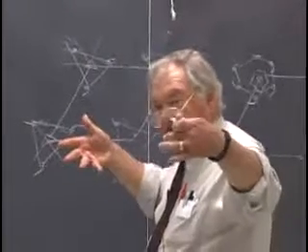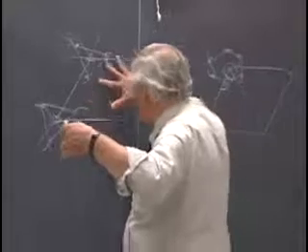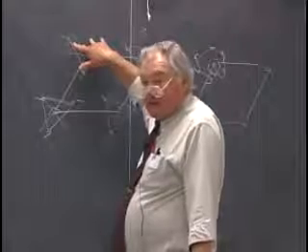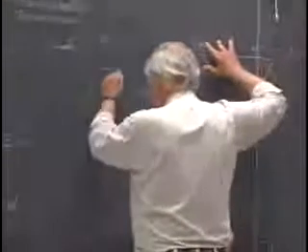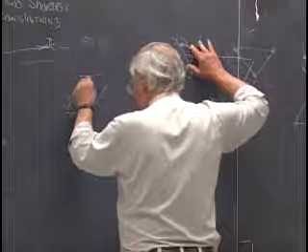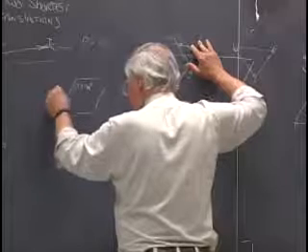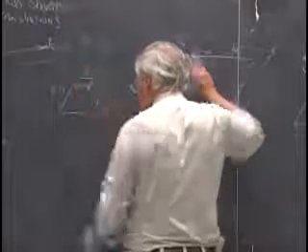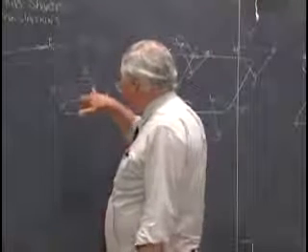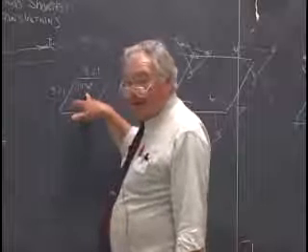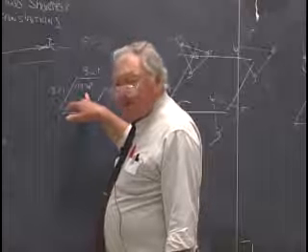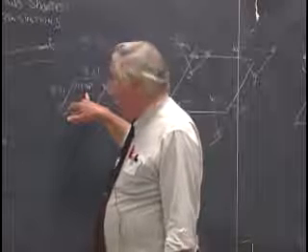specialization of the lattice. Conversely, a lattice can have this specialization only if you place in it a symmetry which demands precisely that specialization. So if you measure a lattice, and this turns out to be 119.99 degrees, and these turn out to be 3.21 angstroms and 3.21 angstroms, that is not a hexagonal lattice, because there's no symmetry in there that demands that this angle be 120 degrees. Okay? And that may seem to be an academic fine point, but we'll see that in due course.